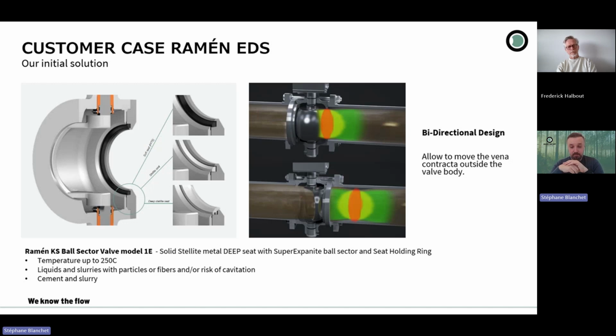And the benefit of this is that, first of all, the ball sector valve is bidirectional, so it can control the flow in both directions. And when you put it in reverse flow, so with the seat facing the outlet, because of that, we have the vena contracta moved outside the body, outside the valve. The vena contracta is where you have the lowest pressure in the control valve system, and therefore the highest velocity. So if you have this vena contracta inside the body, inside the valve, then you have a high velocity, in that case also a lot of solid particles, and then you will completely destroy the body. So we just put the vena contracta outside the valve, and therefore the body is always protected.